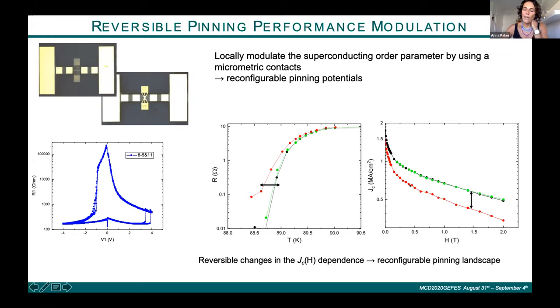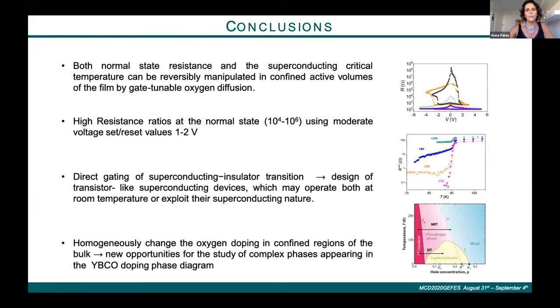And also by applying a pulse of the other polarity, we can come back to the initial state again. So we are able to introduce reconfigurable pinning potentials and change the pinning of the system just by applying these electric fields. With this, I will end with the conclusions of this work.